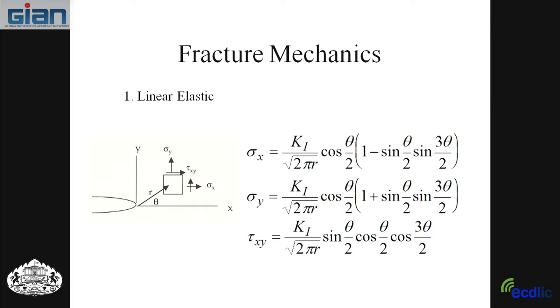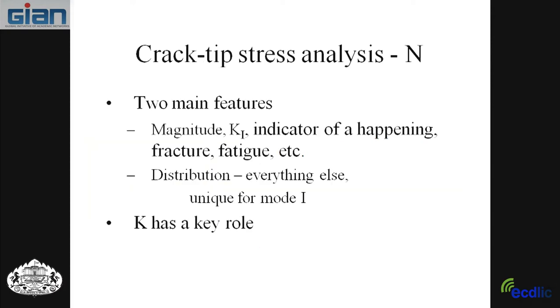No matter how you load, what geometry there is, if it's mode one loading, you always get the same stress terms. And that was an important thing in the fracture mechanics. The important parameter then is the K, and George Irwin called that crack tip stress intensity factor. That is the term that relates the boundary loading to the crack tip stress and gives the magnitude of the stresses around the crack tip.